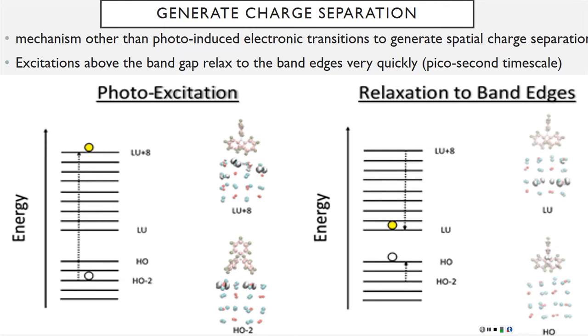On the left, this shows the photoexcitation from the HOMO -2 state, which leaves a hole, to the LUMO +8 state where the electron would reside. If you think about it, this is a very unstable state, and the electron will want to come back down and try to get into equilibrium. To do that, it will relax to the band edges, which happens approximately on the picosecond level. So if both the electron and the hole come to the band edges, that will produce spatially separated charges.